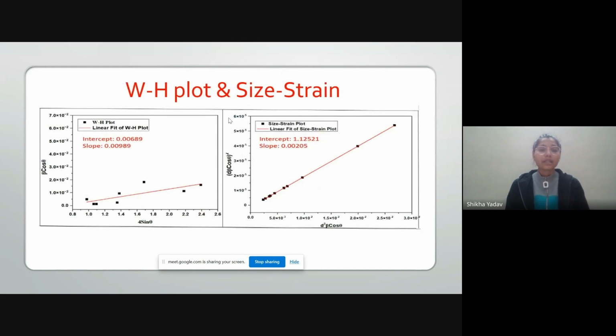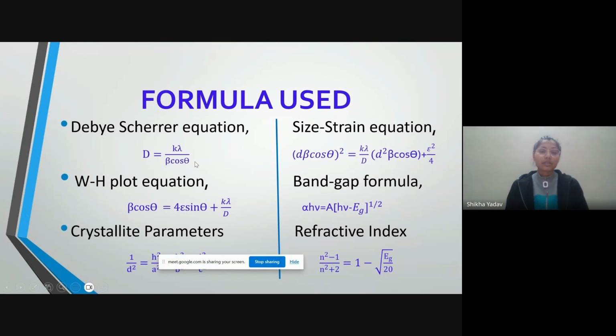Next we'll talk about the WH plot and the size strain. As I said, I used three formulas to get the crystallite size. Number one was the Debye-Scherrer equation: D equals K lambda upon beta cos theta, where D is the crystallite size, K is the Scherrer constant, beta is the FWHM, and lambda is the wavelength of the XRD. Using this formula, the approximate value was 63 nanometers.